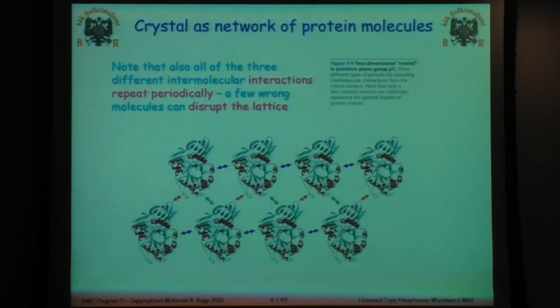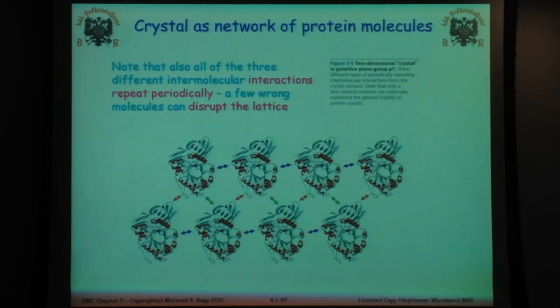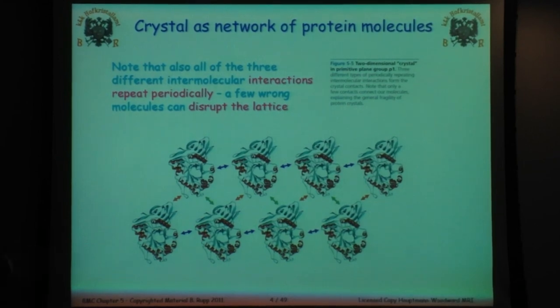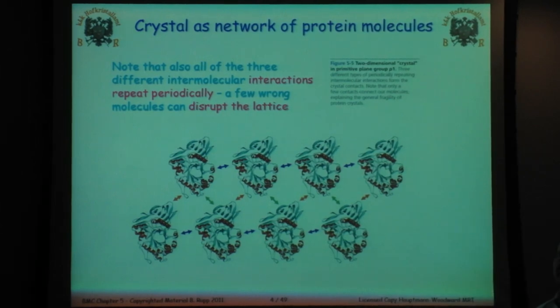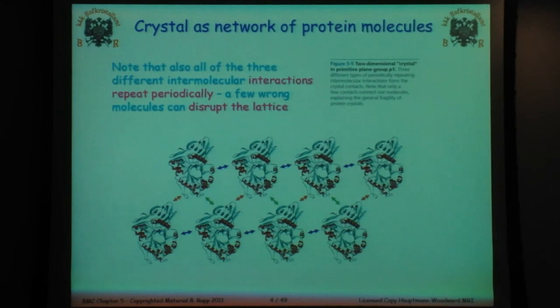The Matthews coefficient says that crystals typically have between 30% and 70% water. So when you think of a protein crystal, you should think of it as more like jello — you couldn't put it on a ring and give it to someone. That fact is important because it shows that the contacts are actually very limited between protein molecules. We can take one of these molecules and see we've got about three crystal contacts, so the actual contacts that make up a crystal are small — on the order of about 10 in a particular crystal.